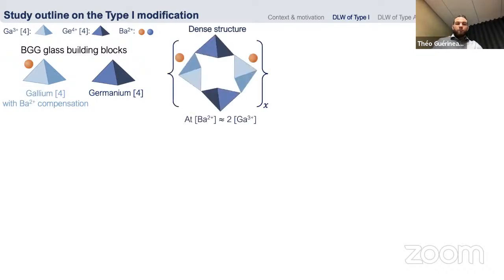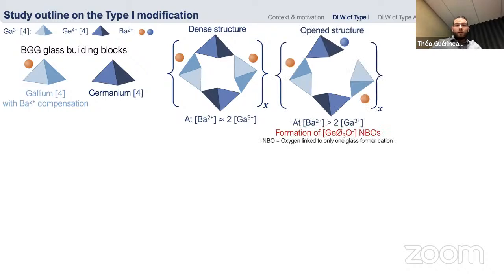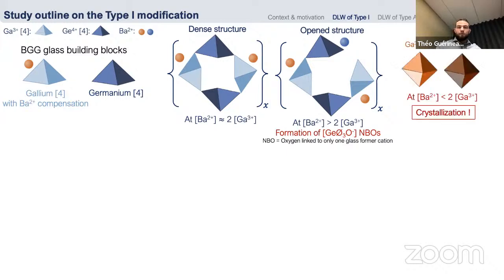When the quantity of barium reaches around 2 times the concentration of gallium, we have a very dense structure. But when we increase more the concentration of barium, there is a formation of non-bridging oxygen on the germanium tetrahedra. The non-bridging oxygens are oxygens that are now linked only to one glass former cation. And we have an open structure.